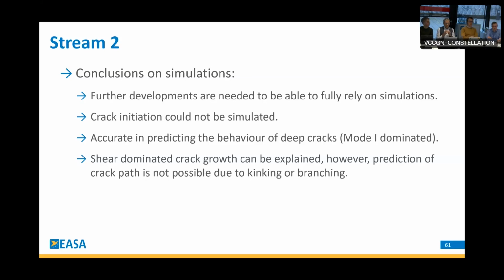Also, we found that really with the tools we could identify, crack initiation could not be simulated. Also, we found it was very challenging to detect it during testing, so that we could stop the test when the crack had just started, and we could investigate that stage of the failure progression. So yeah, crack initiation has been a bit difficult to tackle.